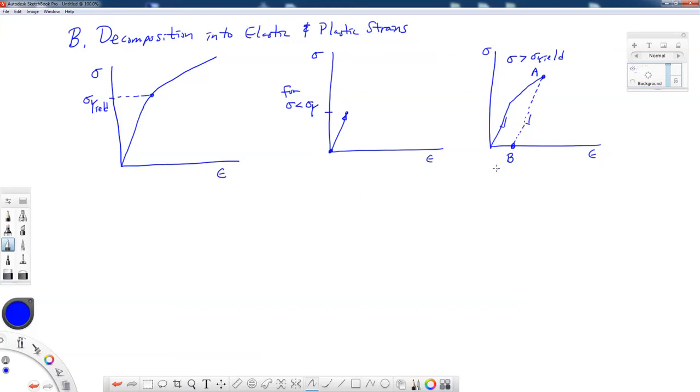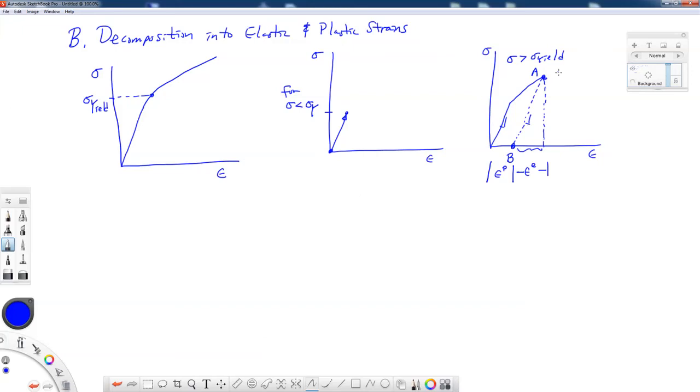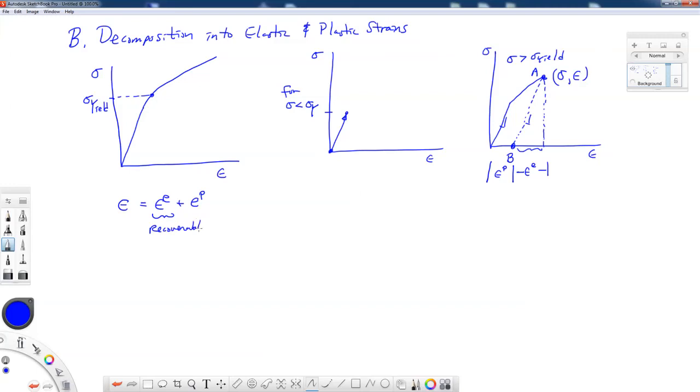The thinking then is that the amount of strain that is left over is known as our plastic strain. And the amount of strain that went away would be our elastic or our recoverable strain. So that means up at this point on the stress-strain curve, I had both elastic and plastic strain components. We're going to assume here that epsilon is equal to an elastic part plus a plastic part, where this is a recoverable or elastic strain, and this term is our permanent or plastic strain.